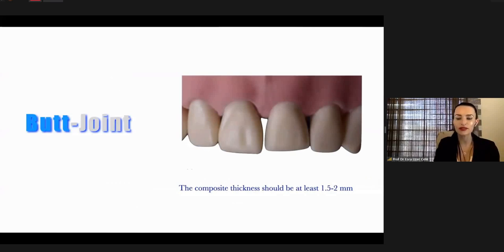In the butt joint design, a reduction of the incisal edge is achieved. The composite thickness should be at least 1.5 to 2 millimeter to prevent fracture of the incisal edge. As I said before, composite resin material is a little bit fragile in thick sections, so we have to preserve this thickness for the maintenance of our restorations for a longer period in clinical conditions.